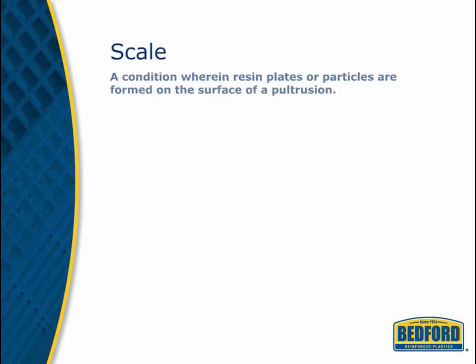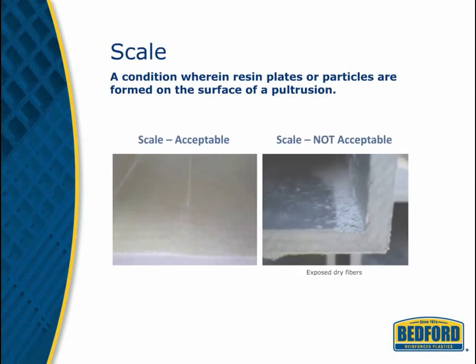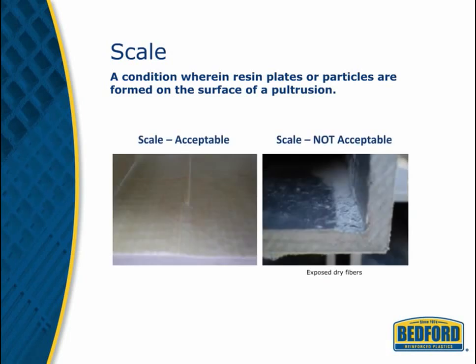Scaling is a condition where resin plates or particles are formed on the surface of a pultrusion. Scales can often be readily removed, sometimes leaving surface voids or depressions. Scaling is acceptable if removal does not expose dry fibers and if dimensional tolerances are met.